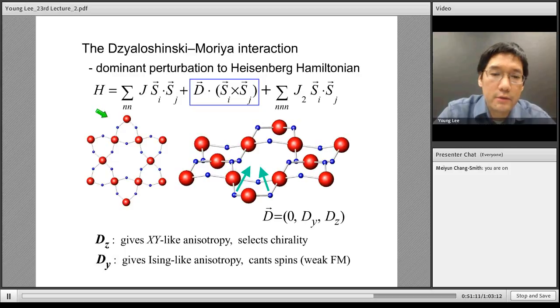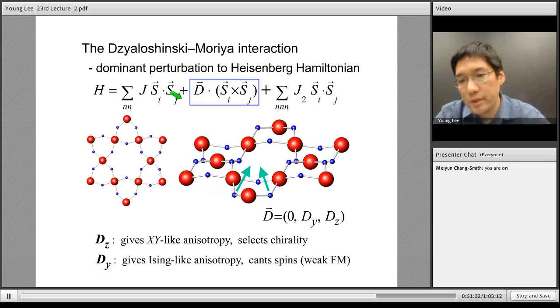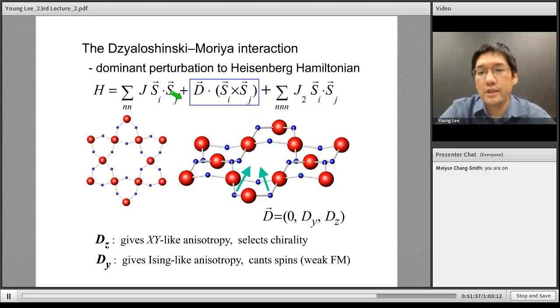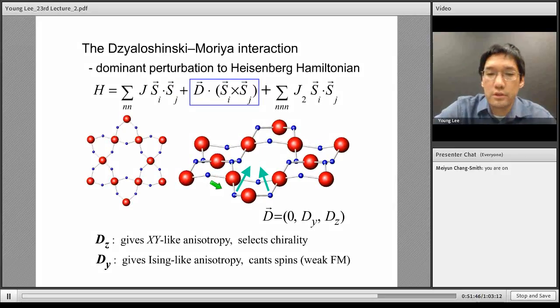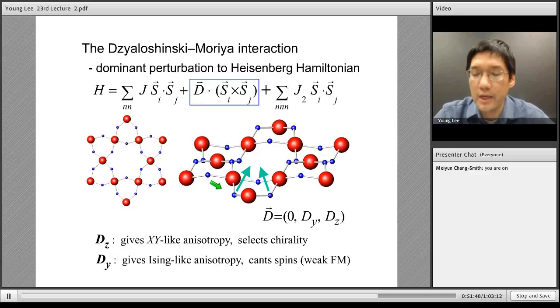So we do expect there to be some superexchange interaction. These are the iron atoms in red, and there's this bridging oxygen atom between them, which can give us this J. But we see that the bond between the irons is buckled. Due to this buckling, there's not a center of symmetry between the magnetic ions, and therefore you can get what's termed the Dzyaloshinskii-Moriya interaction, and it goes as this D vector dot Si cross Sj. And this D vector is determined by the quantum chemistry of your crystal.